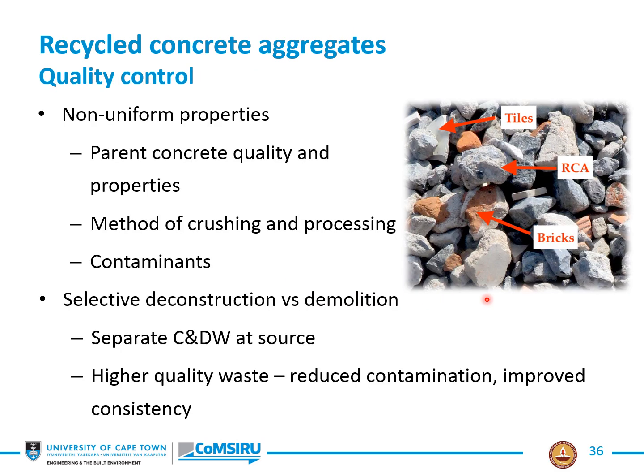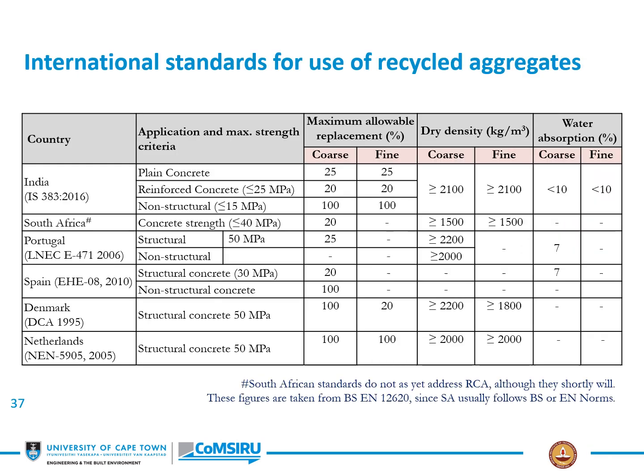Quality control is an issue, however, because we have this variable material. We have non-uniform properties; the parent concrete quality and its properties will affect that, as will the method of crushing and processing, and of course contaminants. Even a small amount of, for example, brick can have quite a big influence on the properties of the material. And so we really need to think of selective deconstruction, where we actually take out the concrete, or the demolished concrete, at source, rather than as a mixed waste. That results in reduced contamination and improved consistency. So QC, or quality control.